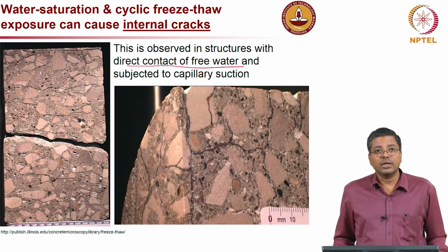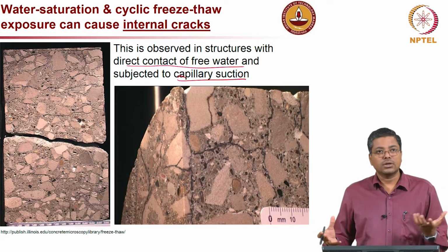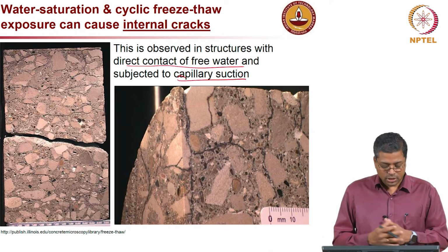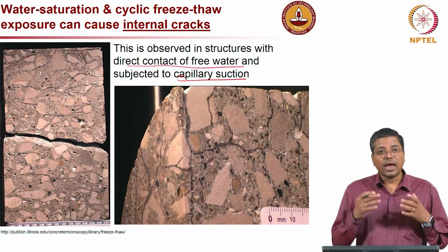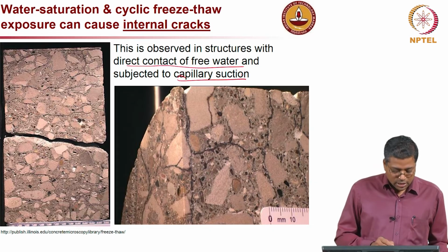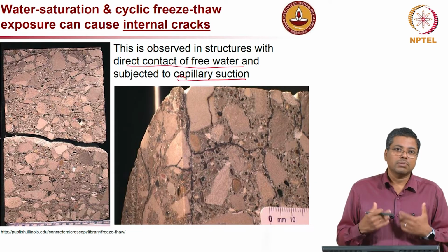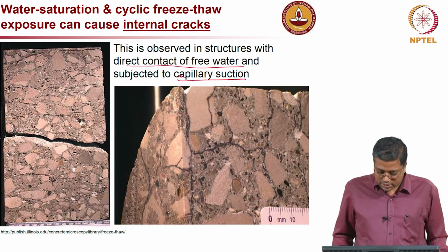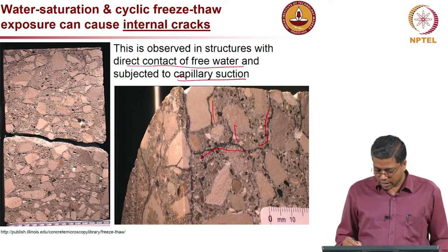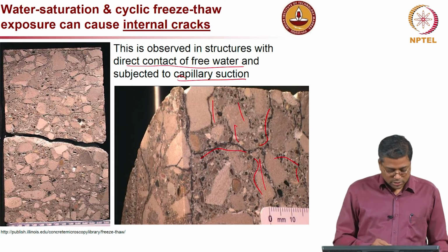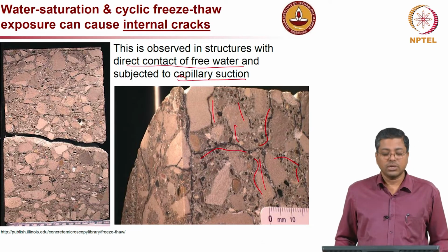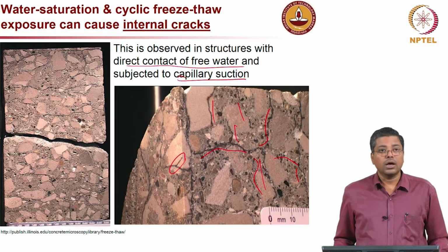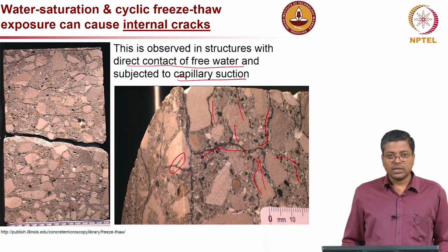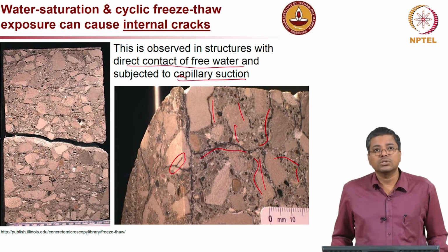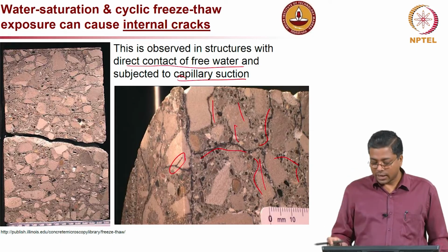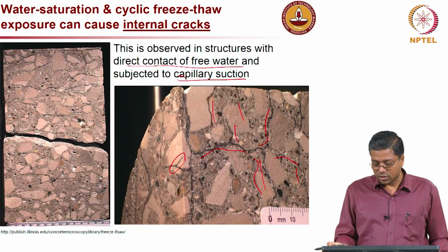So, because of the capillary suction, the internal concrete absorbs all the water from the immediate environment, and when the temperature decreases, that water will become ice, not at the near surface, but inside the concrete, leading to multiple micro cracking, or maybe a larger crack also. Significant cracking you can see in both images, even the aggregates are also cracked. So, all this expansive behavior, the stress induced because of it is very high, which will lead to cracking of the aggregate and eventually of the entire concrete system.